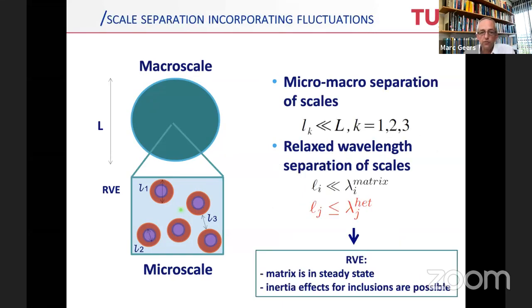Now, it's interesting to step out of this long wavelength approximation and allow for a little bit more. This is what we call the relaxed wavelength separation of scales. It typically means that the matrix has a characteristic wavelength that is still much larger than the sizes of the microstructure, but the heterogeneities, which are the inclusions and possibly also the shells around them, could be of the same order as the wavelength in that particular phase. In such a regime, your matrix is in a steady state, but inertia effects in the inclusions are possible.